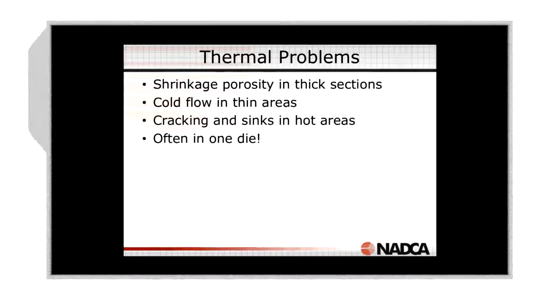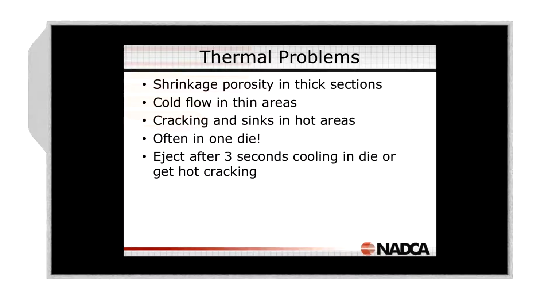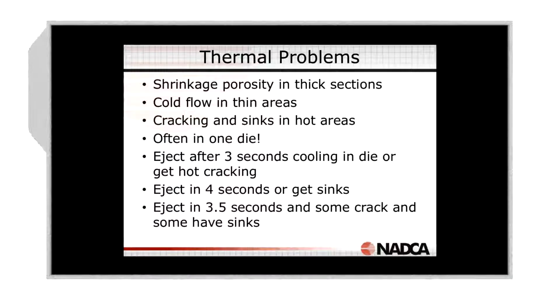Often in one die, you can get a casting that's cracking in one spot and sinking in another, which makes it difficult. But it's very, very common, unfortunately. So the cracking says, I'm shrinking in the die, get me out sooner, eject after 3 seconds cooling in the die, or you get hot cracking. The sink is saying, leave me in the die for 4 seconds, otherwise you're going to get a sink on the surface. So you have this compromise. Over 3 seconds you get cracking, under 4 seconds you get sinks. So you eject at 3.5 seconds and some are cracked and some have sinks, and you say, gee, this is a difficult part. If you'd done the thermal design from the beginning, then it wouldn't have been.